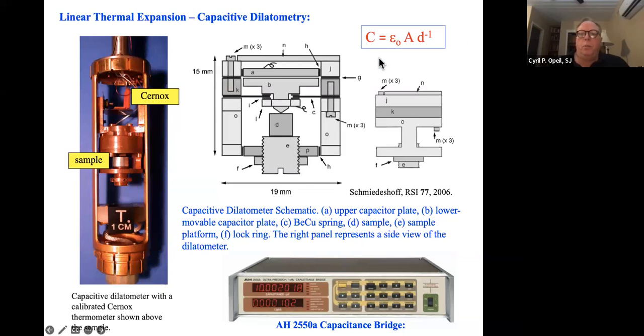This equation says capacitance is equal to this constant times the area of the capacitor plate, which doesn't change, and the permittivity, which doesn't change. But we see that C is proportional to 1 over D. Because this is a reciprocal relationship, if capacitance is measured correctly and accurately, you can understand very small changes. In order to do that, we measure using this capacitance bridge.